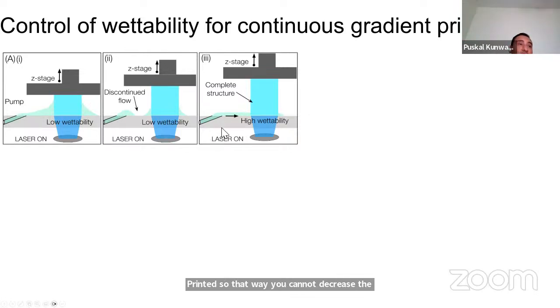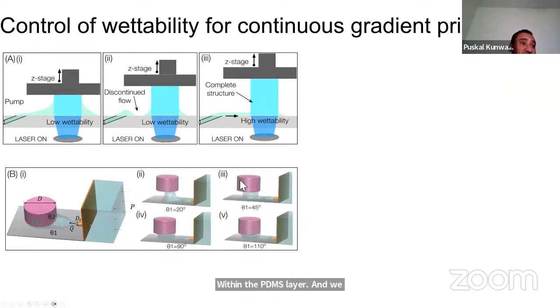Now the other thing you could do is play with the contact angle: try to decrease the contact angle and increase the wettability of the photopolymer within the PDMS layer. We worked with Professor Jen Lee on a simulation where we saw that for a higher contact angle, it is more likely that you will break the flow and result in a discontinued flow. But if we decrease the contact angle, the resin will spread much more and can easily reach the fabrication area. Also, if the contact angle is lower, the volume of resin is decreased. Now how do you increase the wettability or decrease the contact angle?